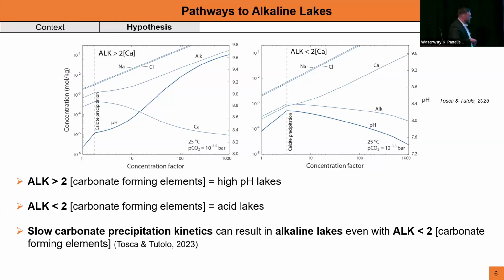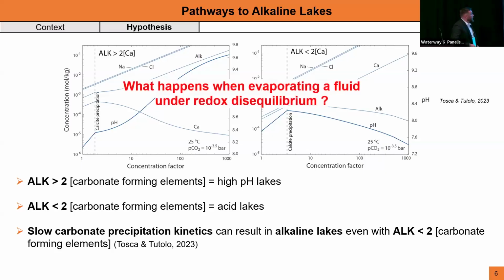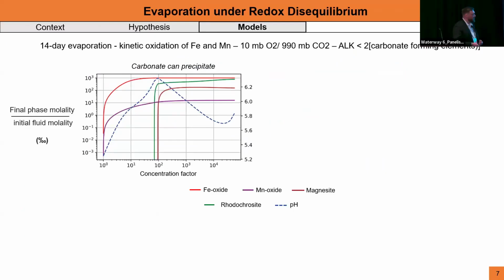It's very important to note that in Tosca and Tutolo 2023, they showed that for kinetic reasons, even when you go beyond the carbonate solubility, you can be hindered by kinetic precipitation and still raise your pH even though the alkalinity is limiting. And so what happens if you do the same thing, but you plug in redox kinetics for manganese and iron? Here we did many models, but I'm just presenting two.